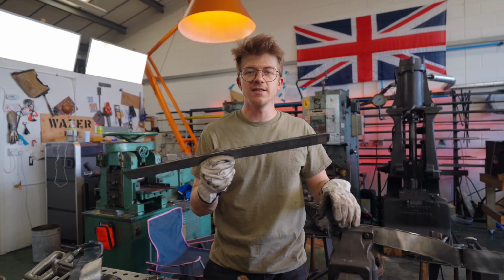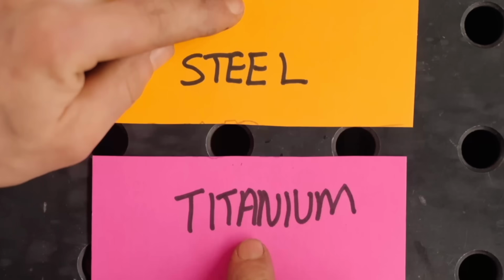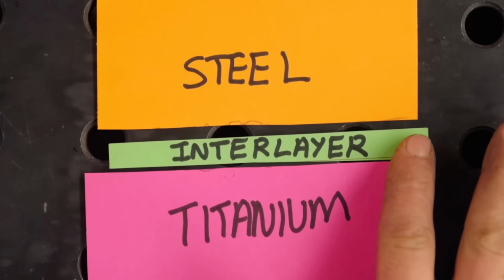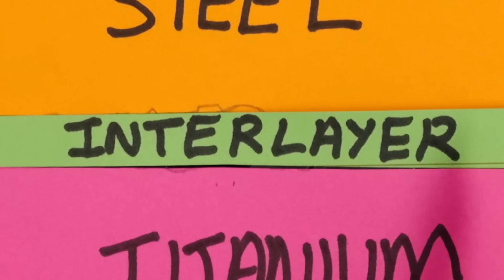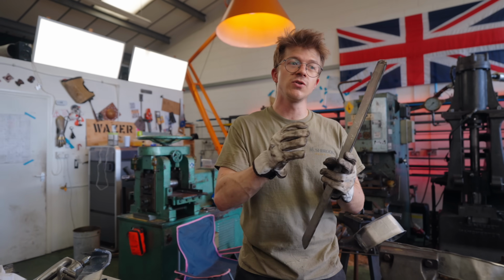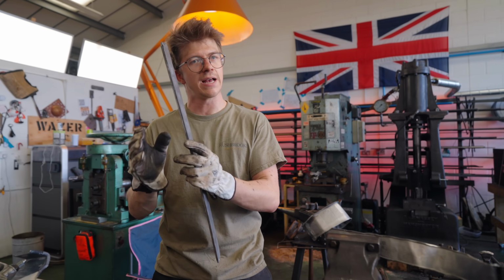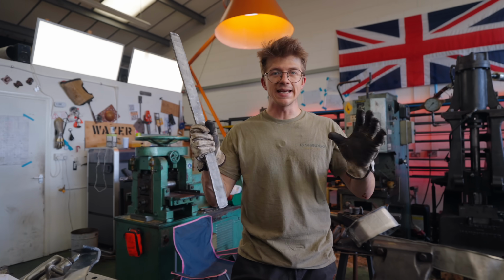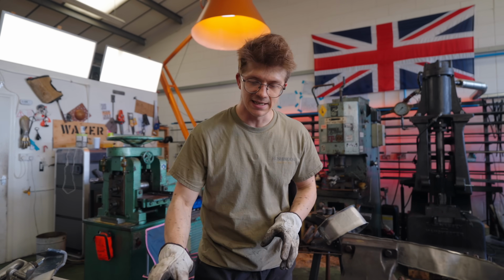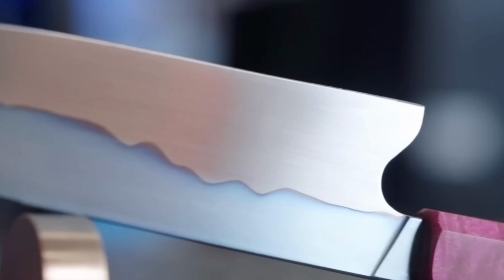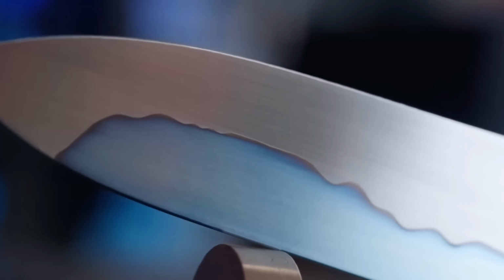That is what's called an interlayer, and as I mentioned earlier, it's a diffusion barrier, so it stops those iron atoms ever reaching the titanium atoms. Nickel likes to bond quite well with titanium, nickel also likes to bond quite well with steel, but it keeps them both nicely separated.